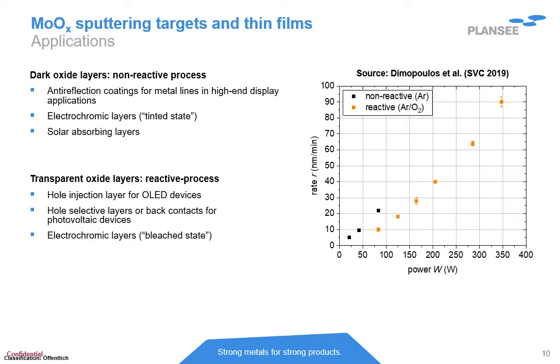Due to that broad range of different properties, these molybdenum oxide layers can be used in different applications. The dark oxide layers, for example, sputtered in a non-reactive process using molybdenum oxide ceramic sputtering targets, can be used as anti-reflective coatings for metal lines in high-end display applications. Also, electrochromic layers can be sputtered from this material, and molybdenum oxides are also an interesting material in solar absorbing layers. If you want to use transparent oxide layers, you can use a reactive sputtering process, and those transparent oxide layers are interesting as hole injection layers for OLED devices, can be used as hole selective layers or back contacts for photovoltaic devices, and also as electrochromic layers.